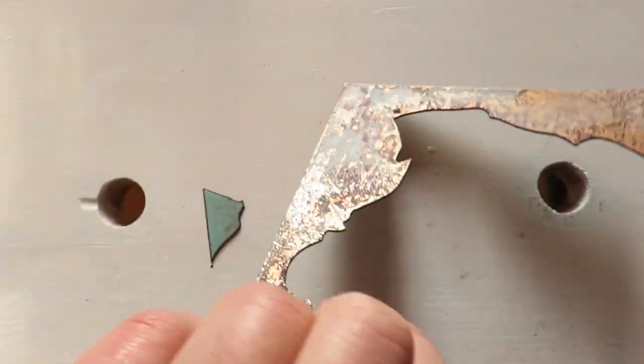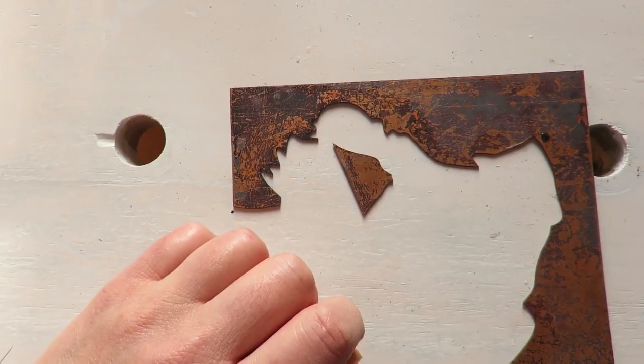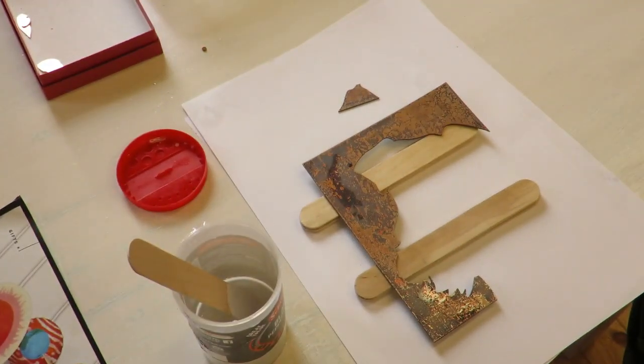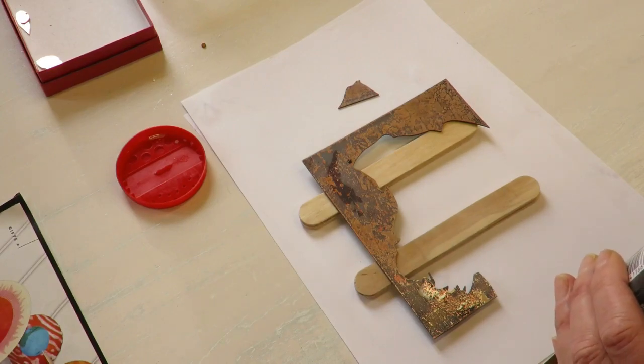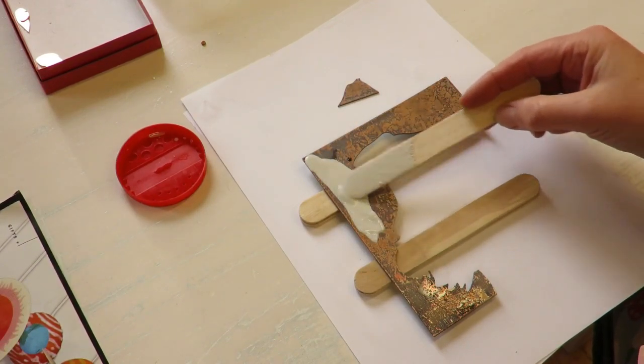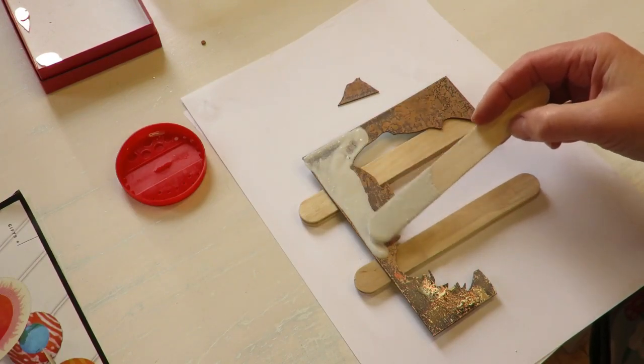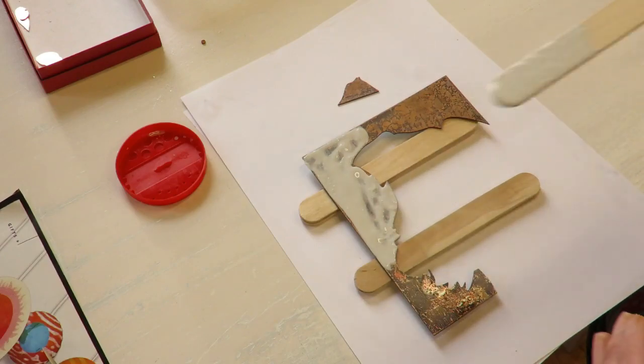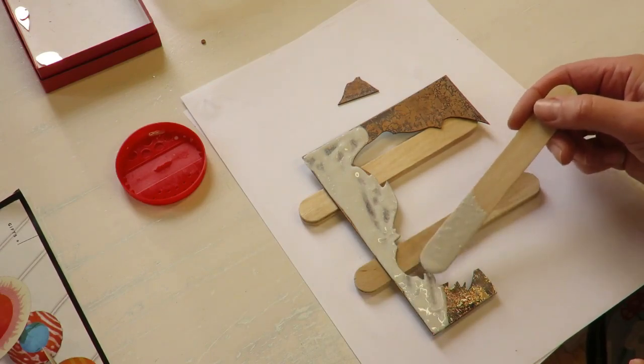I have to do a coat on the back as well. I'm just going to use like an industrial style, very tough enamel on the back, and then I can put one coat on the back of this and do several coats of the glue to make it really nice. I'm putting on this counter enamel, which goes on the back of this piece — it's liquid and I'm just putting it on with a big lollipop stick. It doesn't have to be gorgeous; it's going to be on the back. The only reason to use counter enamel is because you need to balance out the enamel on the front with enamel on the back, because otherwise areas — particularly like this little narrow area — could chip, get fractures, or crack.